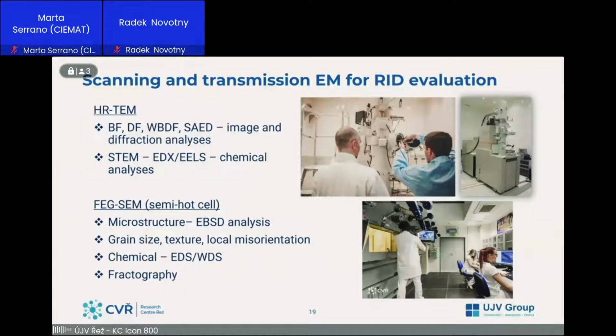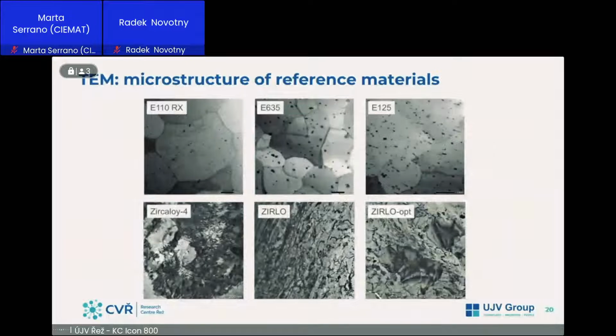What we do by electron microscopy, we do image and diffraction analysis and chemical analysis, and then the results from transmission electron microscopy are completed by scanning electron microscopy, where we perform the crystallographic analysis and grain size, texture, and we observe the local misorientation after irradiation, and as well the chemical analysis we do in low magnification to complete the TEM results. And here are some examples of reference materials, zirconium-based claddings: the Russian E110, E635, and E125 microstructure, and as well the zircaloy, ZIRLO, and optimized ZIRLO different microstructures.